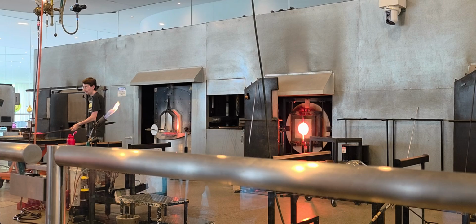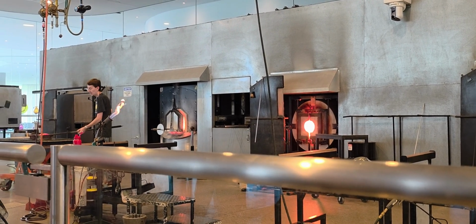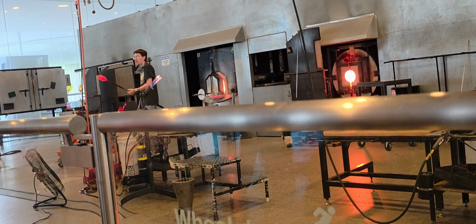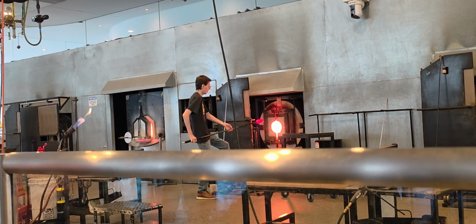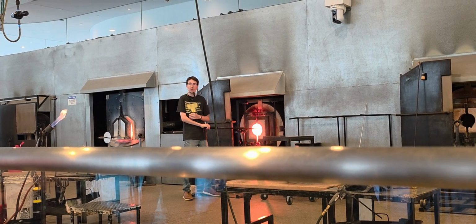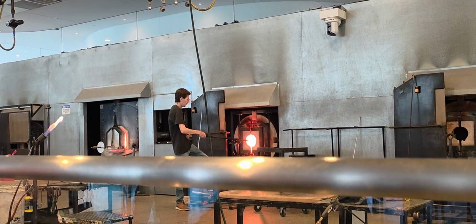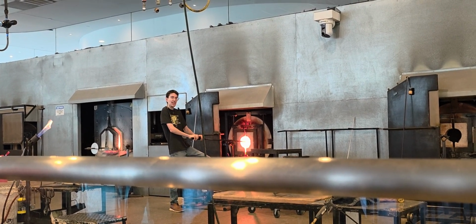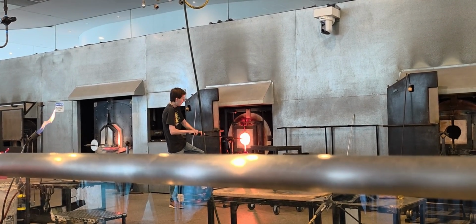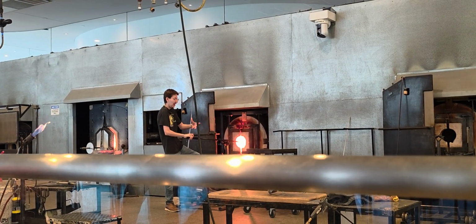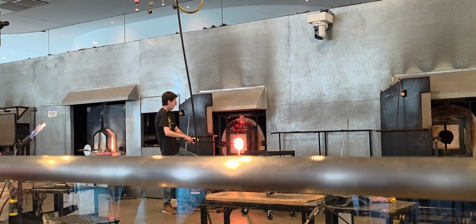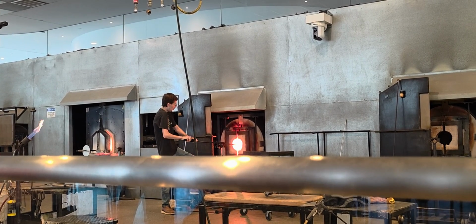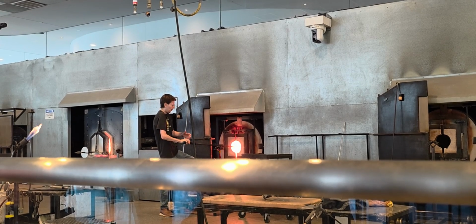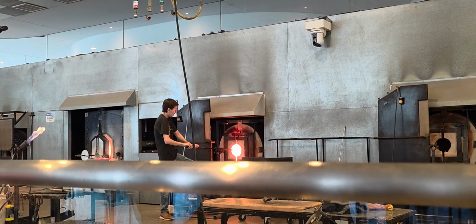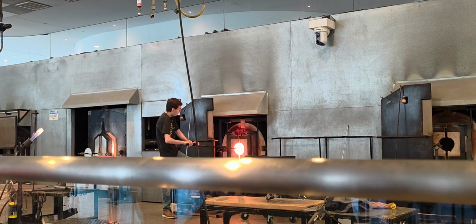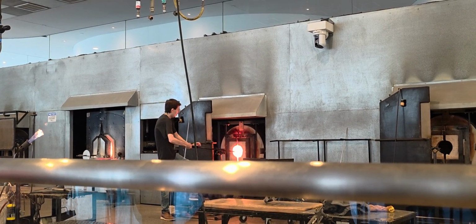And what that does is relieve any stress that can be built up in the glass. So glass is a really good insulator, and what happens is the outside cools down quicker than the core. We're going from a liquid state to a solid state, so all the molecules moving around are going to start to slow down and squeeze on themselves. They can create about 10,000 pounds of pressure per square inch. And what that can do is actually crack and sometimes make the glass explode. So we don't want that to happen to the pieces we make. So we let them cool down slowly and more evenly, and it relieves all that stress. It's a process called annealing. It's very similar to what we do with steel to temper or anneal steel as well.